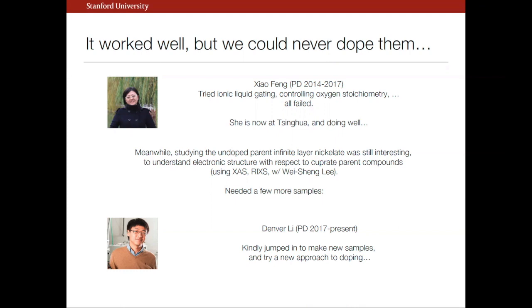But at least for the undoped nickelates that had been studied, somehow there was very little work on the electronic structure. The first of a series of very important accidents, so good fortune, was that we started to work with Lee, who was interested in using XAS and RIXS to study this system. And the typical laboratory thing happened. He left. This started to get interesting. We needed a few more samples. And then Li had just joined later that year and was working on perovskite nickelate membranes. Membranes are another kind of activity in the group. He kind of jumped in to make additional samples, and we revisited this notion of doping.